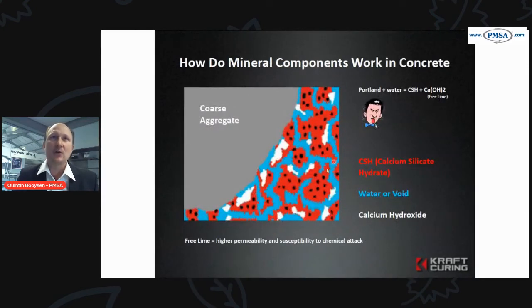Moving now in, so we've gone in, here's your coarse aggregate. This could be a sand particle, and the water and your gel structure that we spoke of earlier. So what it starts to produce is, you have your Portland cement plus the water, and that generates what we call calcium silicate hydrate, or more commonly known as CSH.